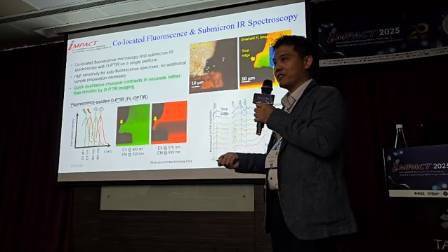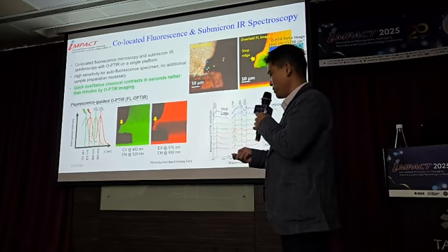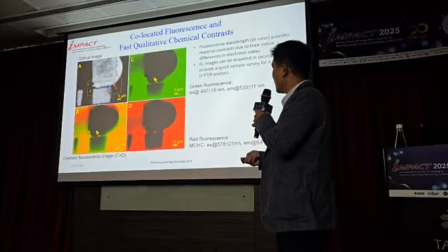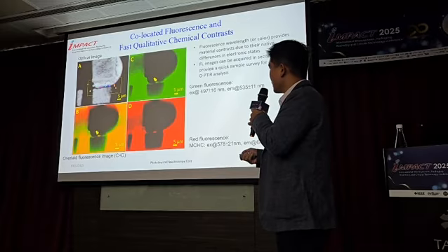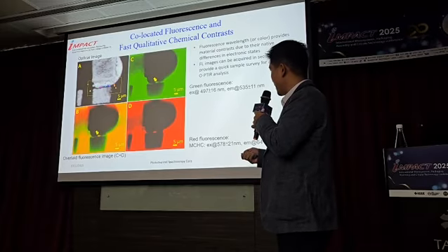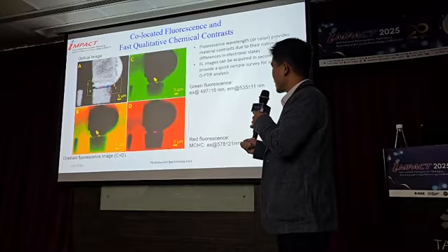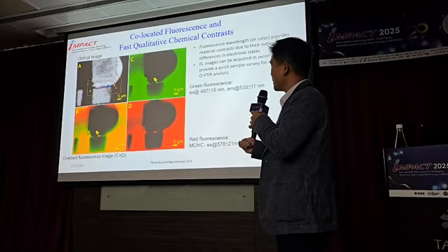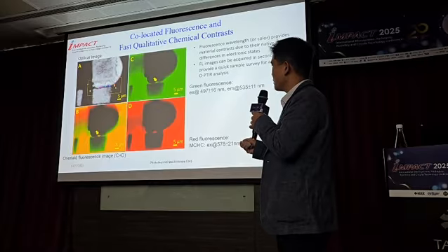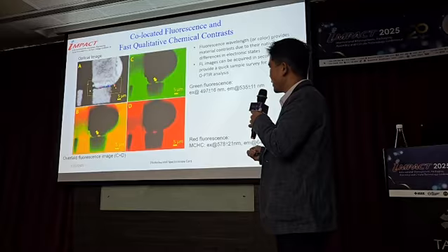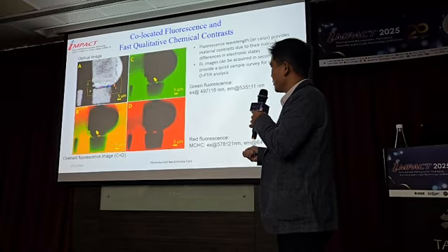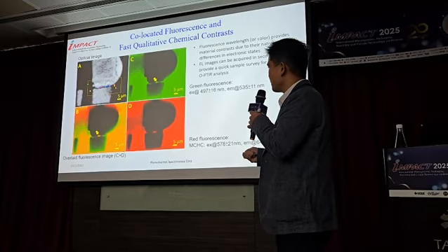We save a significant amount of time doing this fluorescence imaging work. As an example, we have contamination settling on the surface of the copper here. It blocks the solder from joining to it. Using fluorescence imaging, we can quickly identify where the region of interest may be, and we can clearly see that this area is fluorescing.